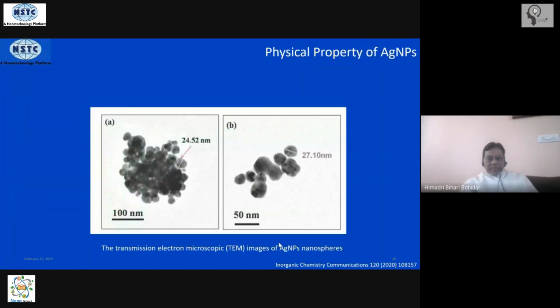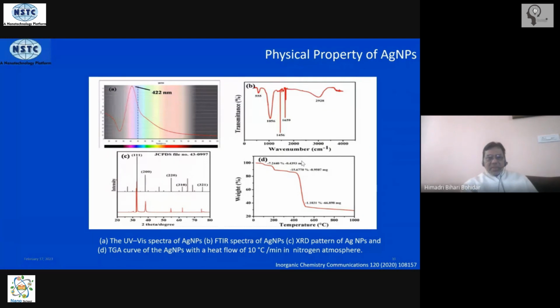Okay. So this is the picture of the silver nanoparticles here. The typical size is about 24 nanometer. Some particles have a bigger size, but they're more or less about 20 nanometer in diameter. UV visible spectra give a clear peak at 420 nanometer, which corresponds to the bluish region of the spectrum here. You can see it here. This is a signature